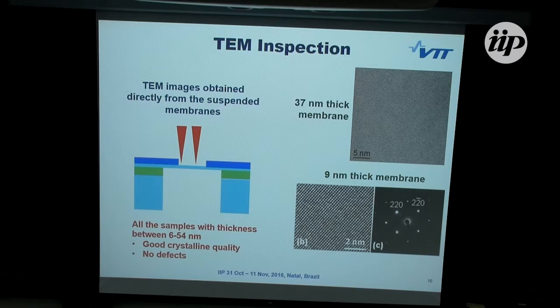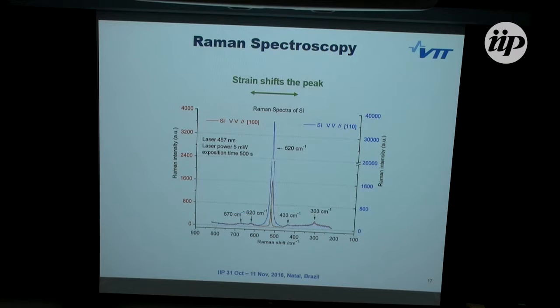And these were taken directly from this. So we had a special sample holder in the TEM so that we didn't remove the membrane from the wafer. We used these kind of samples, which actually created one problem: we couldn't estimate the strain from the diffraction pattern because the focus plane was a little bit difficult to define in our TEM setup. So we had to do something else to estimate the strain. And that is actually Raman spectroscopy.